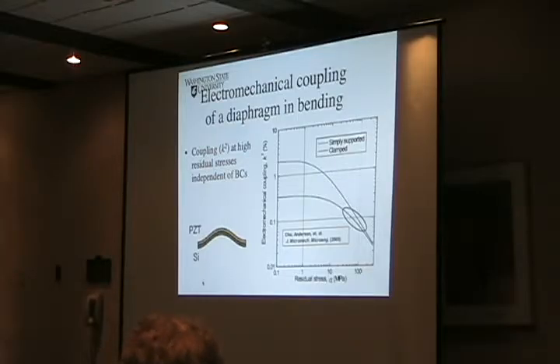But then came up the question that a lot of times when you work with small membranes and small structures, you make small oscillations and deflections. But our device doesn't work using small oscillations and deflections. We push the bejesus out of it. We pressurize at 25 kPa, and we'll take one of these 3 micron thick membranes, 3 millimeters across, and do an out of plane displacement of about 150 microns. So we're not bending it anymore. It doesn't look like this.